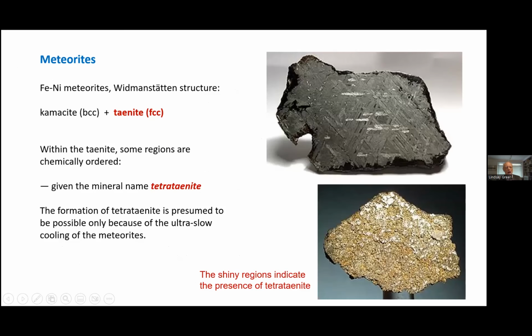Then we come forward a decade or so to people looking at meteorites. You're probably aware that these patterns within meteorites were very important historically in indicating that metals are actually crystalline, so you're getting crystalline orientations here. Not all meteorites are metallic in this way, but some of them are. They are again typically based on iron and nickel, and one of the crystal structures within them is just the one we talked about already, this face-centered cubic.